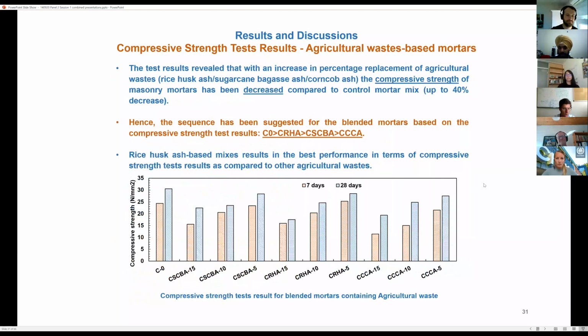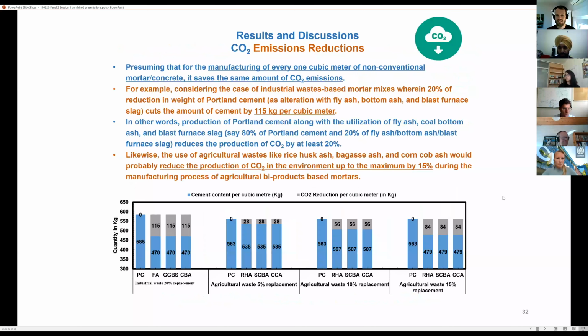Likewise, for the agricultural byproduct based mortar mixes, we have results up to 28 days. In this case, we find a significant reduction, but for the lower replacement levels, there is less reduction compared to the control mix. One can say that the best performance was by the RHA based mixes, then the SCBA based mixes, that is sugarcane bagasse ash, and then the corn cob ash based mixes.